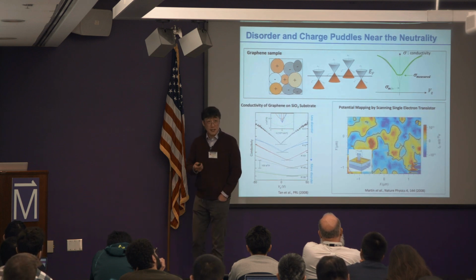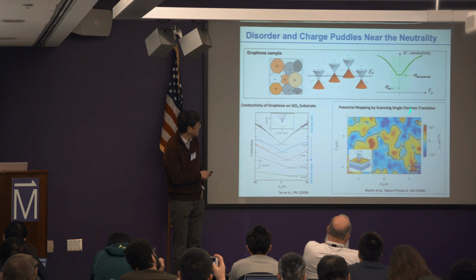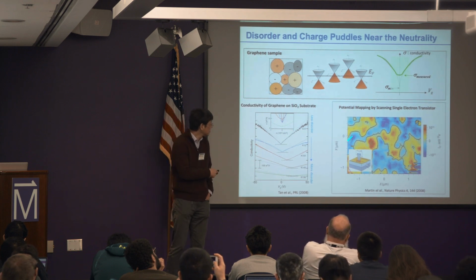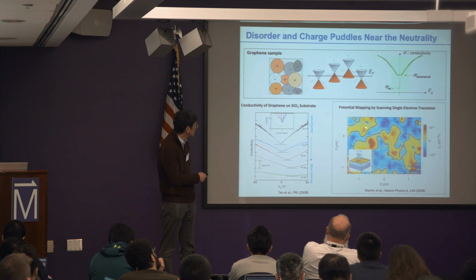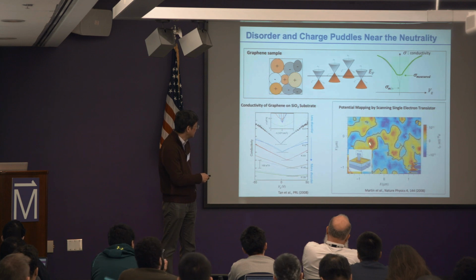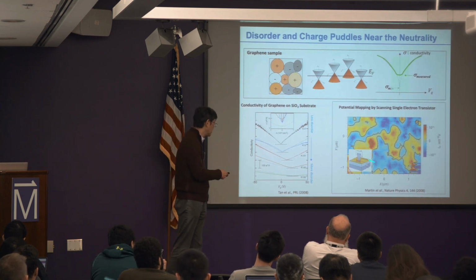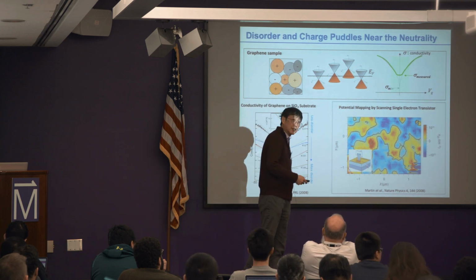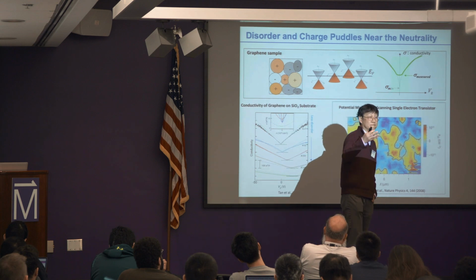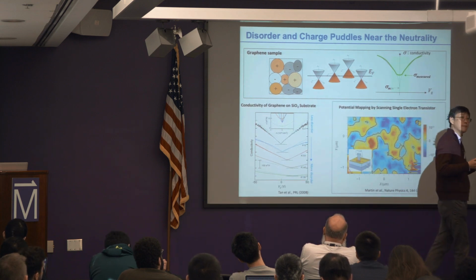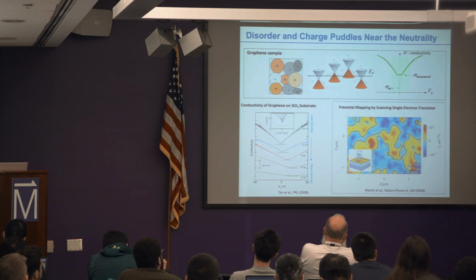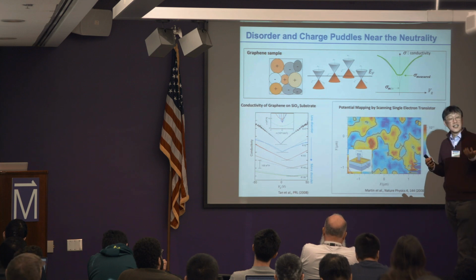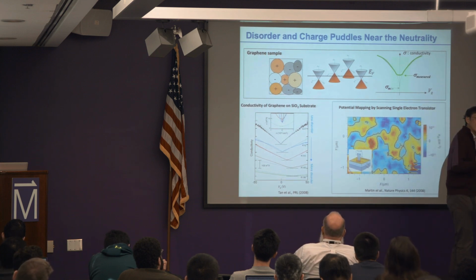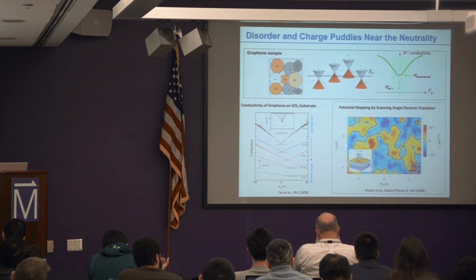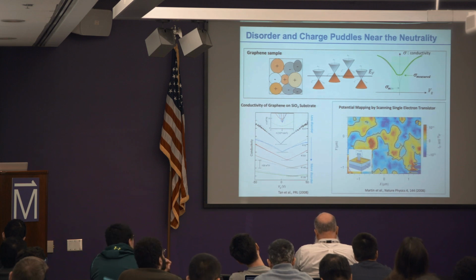Also, there are scanning probe microscope measurements, for example scanning tunneling microscopy, done by Yacoby's group 10 years ago, showing that samples have electron-hole puddles separated by a few hundred nanometers to microns length scale in this type of images, right? Note that this was already 10 or maybe 12 years ago, and the sample back then was much more disordered than the samples we can have now. The van der Waals stacking technique I just introduced in the beginning was only discovered just after this experiment was done. So this shows the typical graphene sample sitting on a silicon oxide wafer, the state of the art about 10 years ago, right?